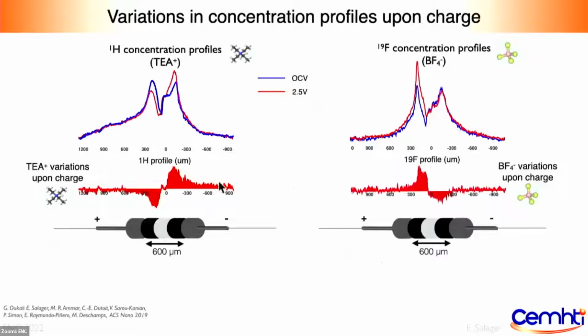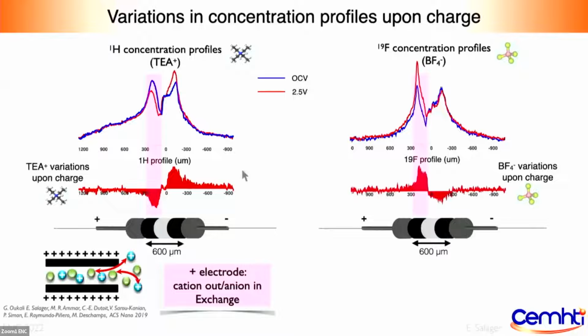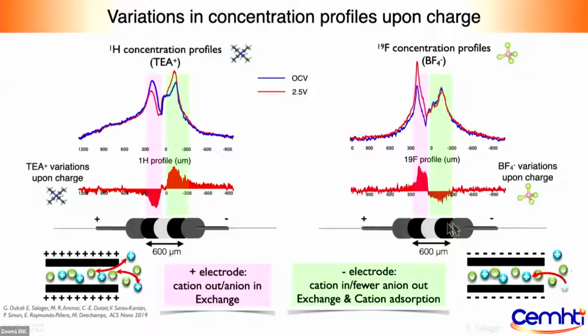And so to exploit and better understand these changes, what we did was to subtract the profiles at the beginning and when it was fully charged. And what we observe is that the cations are expelled from the positive electrode, and at the same time, the anions are absorbed inside the positive electrode. So this is confirming this exchange mechanism. And when we compare it for the negative electrode, what we see is that the contribution of the fluorine anions at the negative electrode is actually much smaller than at the positive electrode. And this is indicative that at this electrode, the mechanism is slightly different. So that was quite interesting.